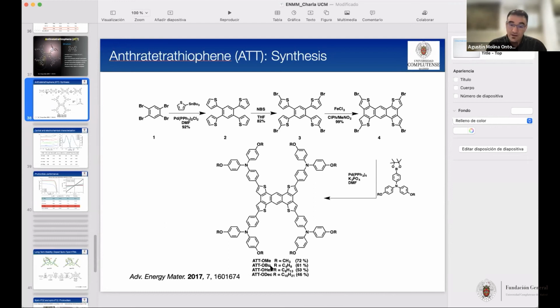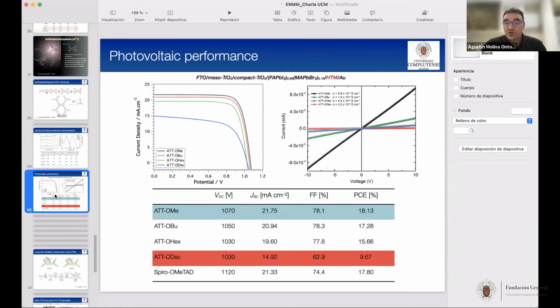On the other hand, when you have a C4 butoxy group, it works more or less the same, within 1%, but what matters is the formation of the film. Also, by introducing longer alkyl chains, you are affecting the conductivity as well. Okay, so you have a good idea of what's going on.